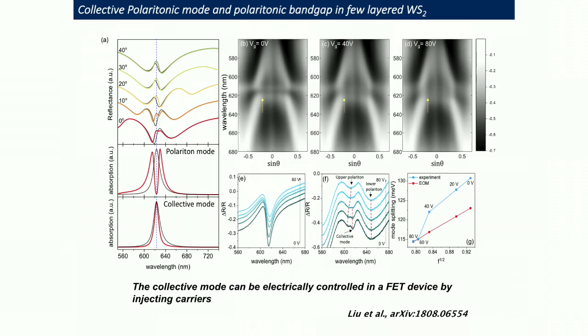So basically, this is a very classic phenomenon in this polaritonic business. But what we found was in this system, in this collective system, and since we can electrically tune it, the moment this new mode emerges, we have a nonlinear increase in the mode splitting, in the anti-crossing behavior, as a function of the square root of the number of excitons. It should have followed this linear pattern, but it does not, and it shows this nonlinear behavior. So this is another evidence showing that we have this collective behavior in the system.